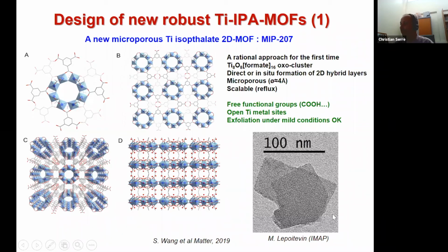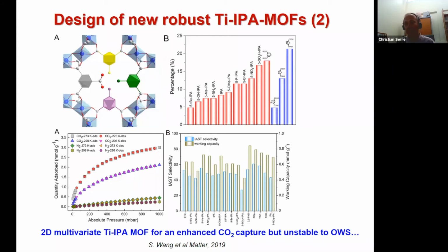You can see these nice TEM images that we collected recently after exfoliation. So this is probably interesting for many applications where 2D materials are of interest. But we also tried the typical strategy of a multivariate ligand mixture during the synthesis. And we could obtain a significant replacement of the trimesic acid by different derivatives of isophthalic acid and also some 5-membered heterocyclic ligands. And it has some consequences in terms of CO2 capture. You can tune the capacity and the selectivity.